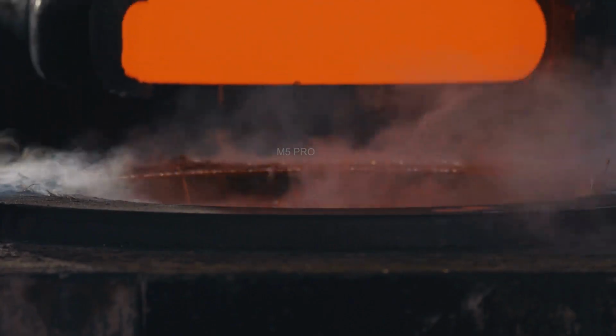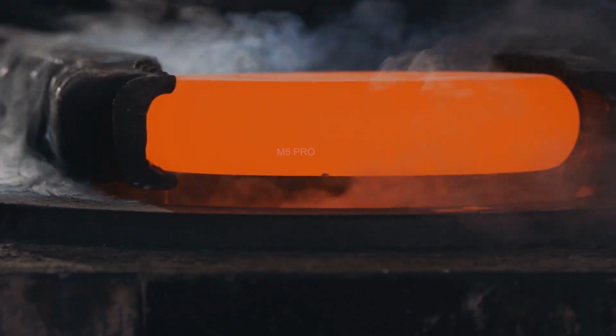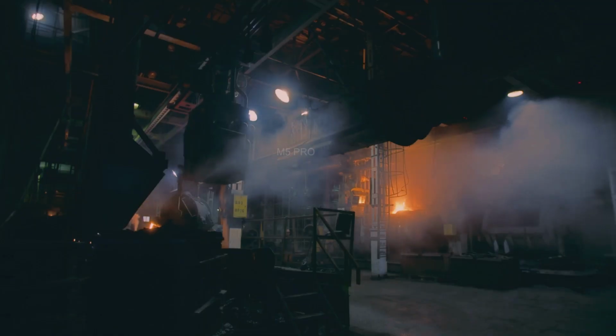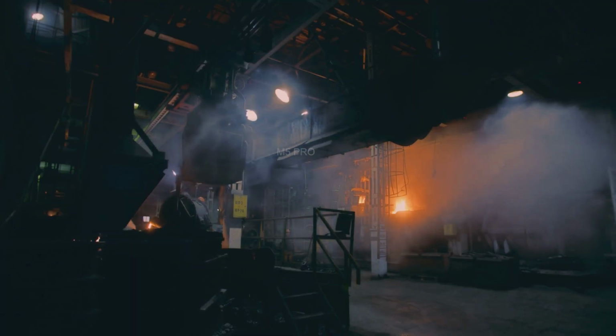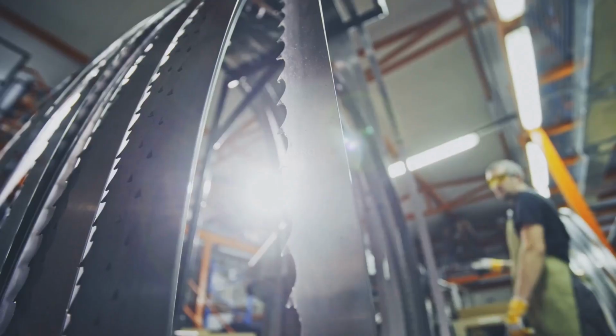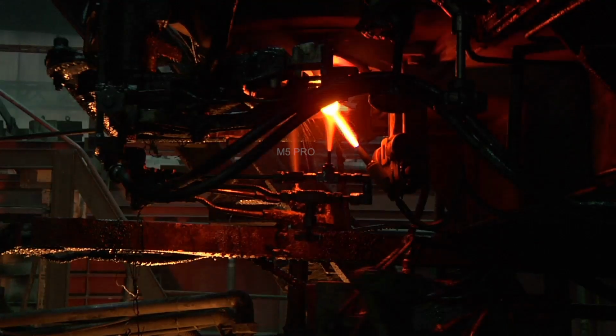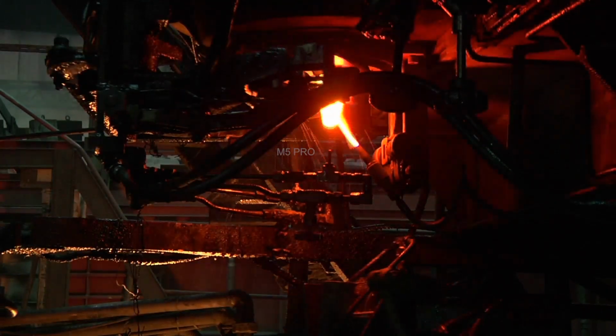Once the blades have soaked at this temperature and the transformation to austenite is complete, the most dramatic moment in the factory arrives: the quench. This is the point of no return. The glowing hot blades are rapidly removed from the furnace and immediately plunged into a large vat of oil. The sudden, extreme cooling is a massive shock to the steel system.